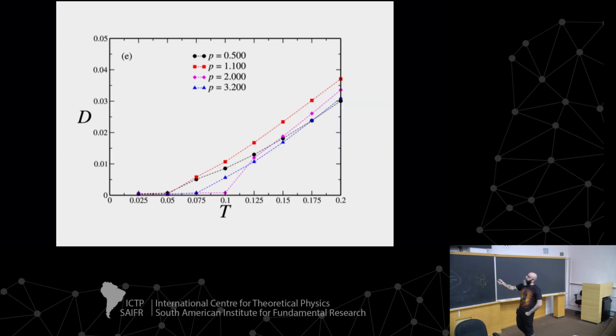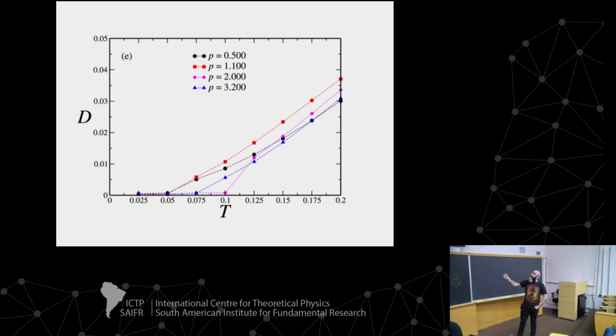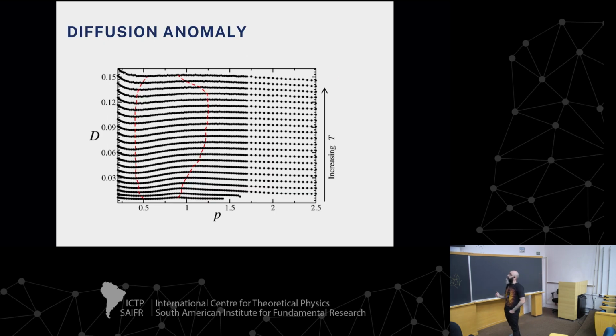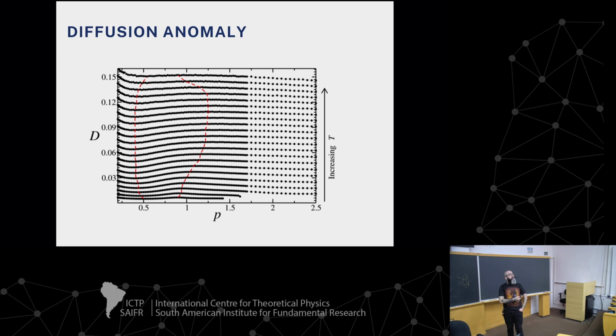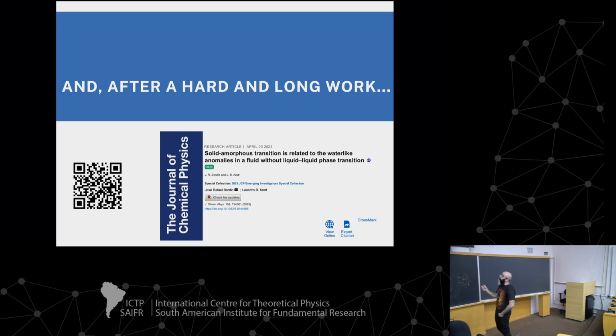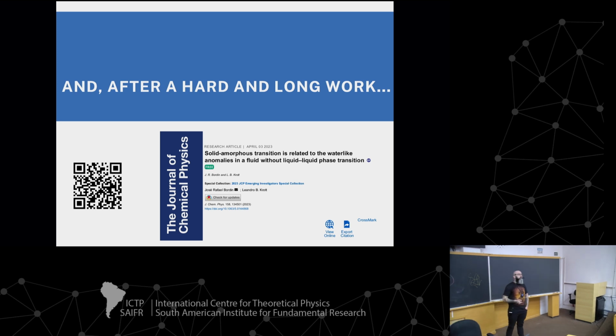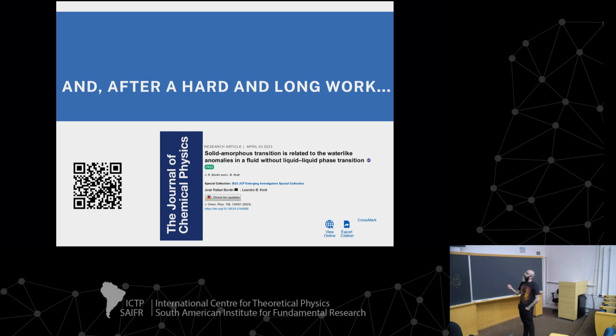And well, this is just the diffusion coefficient against temperature to show how it decreases. In some cases, it goes straight to 0, and in some cases, more smoothly in the amorphous to fluid transition. And here is the diffusion anomaly. We increase the pressure, and the diffusion increases. Okay, so, in a long and hard work, analyzing a lot of points, we built this nice work.